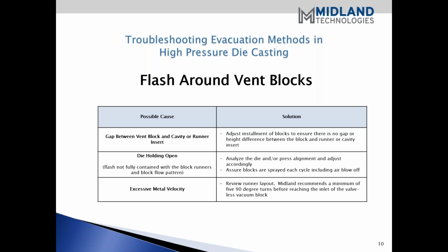Assuring yourself that you've got the blocks preloaded. When you install blocks, they should be preloaded to the same height as the cavity insert. And we indicate here a runner insert, and what that denotes is a steel block, H13, same heat treated so it won't get peened over, same as a block. We want to preload those all at the same height in the cavity, the same as you do a cavity insert, because you want to make sure that you don't have any leakage when you close the tool up.